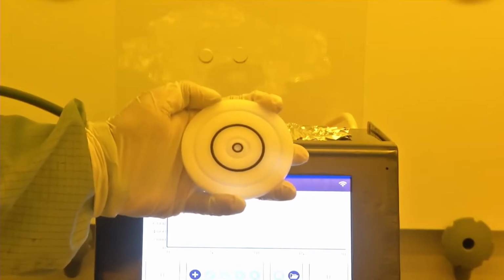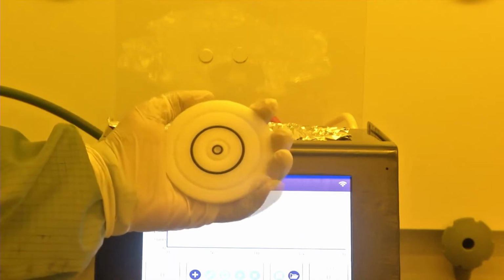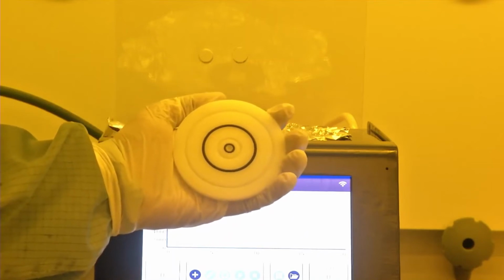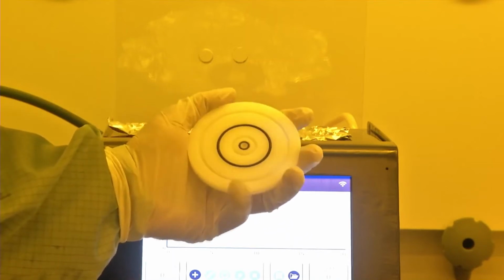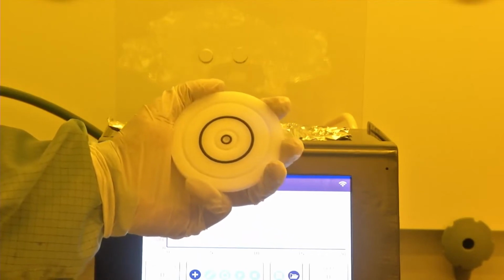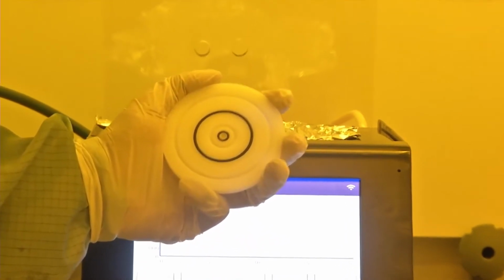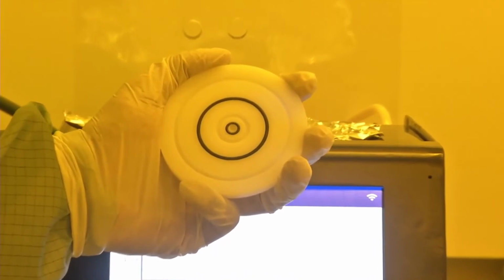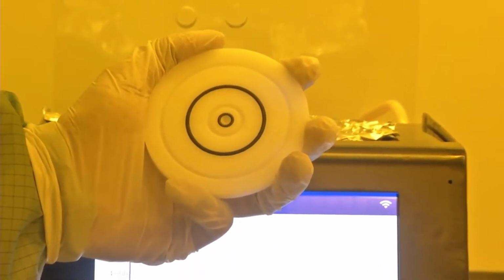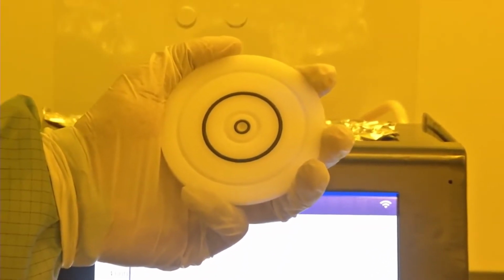Depending upon the substrate you want to spin coat on, you can put the dedicated O-ring. The O-ring should be put after applying vacuum compatible grease so that the contact between the substrate, which is the silicon wafer, and the O-ring is leak free.